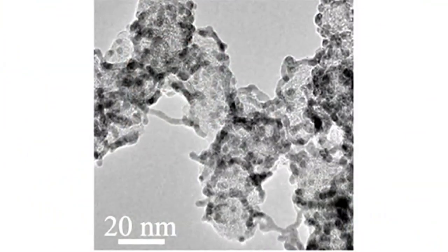Shortly thereafter, we looked at a very similar system like palladium nanowires. In this case, palladium is much less expensive than platinum. We looked at whether we could develop an ultra-thin nanowire catalyst of this platform. Once we examined the properties of those ultra-thin palladium nanowire catalysts, we then moved on to deposit a monolayer of platinum atoms. And we saw very significant increases in activity as a result of that platinum monolayer deposition.